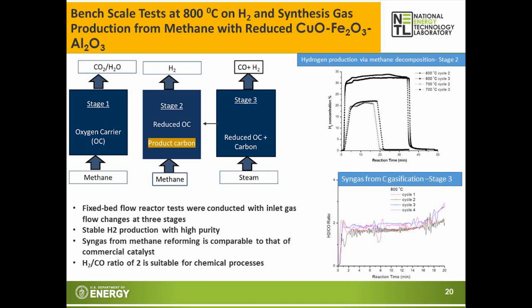Then after that, we introduce steam to gasify the carbon that's produced from the methane decomposition to produce syngas. And these are the syngas production data in stage 3. And the hydrogen to carbon monoxide ratio of 2 is seen in the cyclic test, and that's very useful because we can use that for the downstream chemical processes, and we get very stable performance.